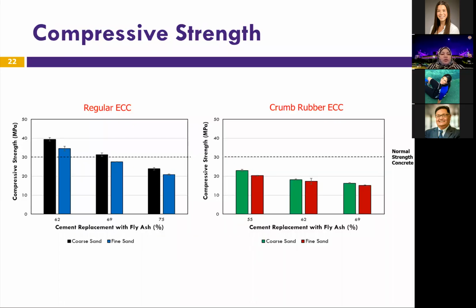So this is a slide that shows the compressive strengths of regular ECC and crumb rubber ECC with cement replacement with fly ash and coarse sand and fine sand. So as shown in this slide, the ECC with coarse sand exhibited a higher compressive strength compared to the one with fine sand. This was the case for both the regular ECC and the crumb rubber ECC. In addition, replacing sand with crumb rubber caused a reduction in the compressive strength. This drop in the compressive strength of the ECC with crumb rubber is attributed to the defect-like behavior of crumb rubber in the ECC specimen. It's probably reducing the bonding within the cementitious matrix, in addition to the fact that rubber has a lower stiffness.